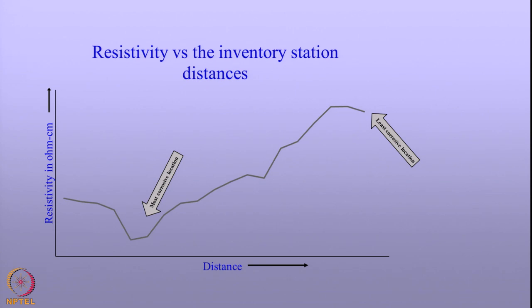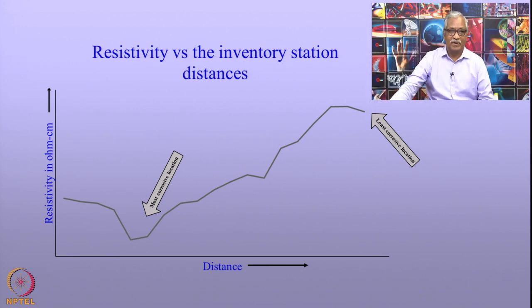Let us look at the usefulness of the resistivity. What is given here is a plot of resistivity in ohms versus the distance in a soil typically measured, it is a schematic of it. What you notice here is that resistivity is not uniform all through, as expected the soil chemistry changes. And as you notice, wherever the resistivity of the soil is very low, that refers to the most corrosive location, and where the resistivity is higher, it implies that the soil is least corrosive.